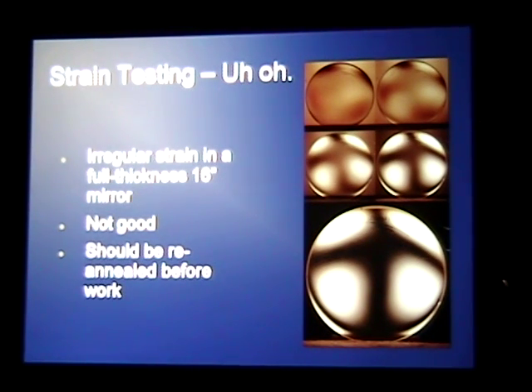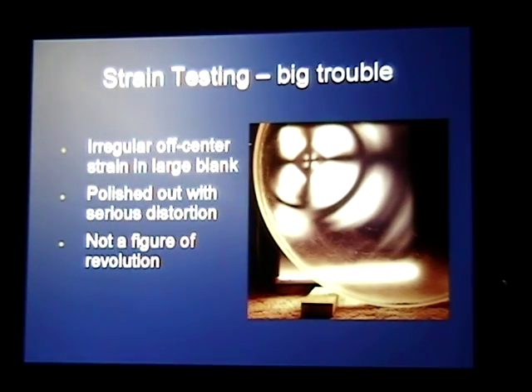Annealing, by the way, is heating up the glass to a particular temperature called the anneal point. You hold there for a short period of time, and then you slowly lower the temperature, on the order of a degree or two per hour, depending on the annealing schedule of the material. So that's how you fix it. Of course, when you do that, the shape of the mirror changes, and anything you polished in is trashed, and you need to regrind and repolish the mirror. This is a bigger blank with really bizarre, stronger, multiple bullseye patterns of strain and did not polish out to a figure of revolution, and I had to reject it.